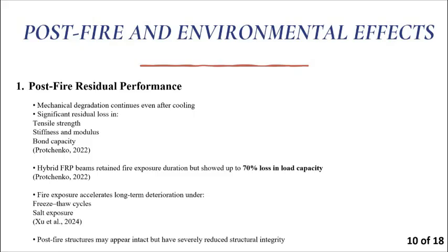So the FRP bars do not recover their original strength. After fire exposure, the tensile strength becomes much lower and the stiffness is also reduced. So this means that the structure cannot carry the same load as before. And in some fire tests, beams lost up to 70% of their load capacity after just 2 hours of fire, even though they did not collapse during the fire. So I hope you get the point.